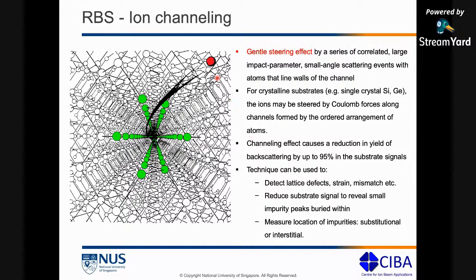And what channeling does: when you have an amorphous substrate, you have an incident ion, it backscatters, it gives you a huge backscattered signal. When you have channeling, what's happening to the incident ion? It basically channels into your atomic rows. So what's going to happen to the backscattered signal? You're going to have a reduced backscattered signal. So under perfect or optimum channeling conditions, your backscattering yield drops by up to 95%. Okay, and I will show you how the spectrum looks, compared to an amorphous substrate, or a random spectrum, as against a channeled spectrum.